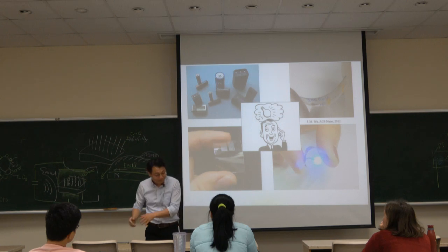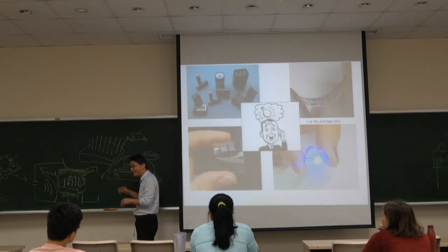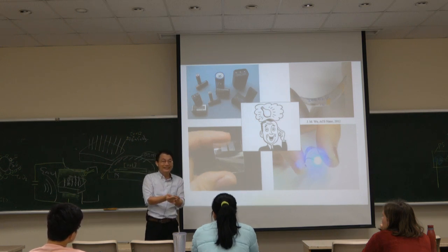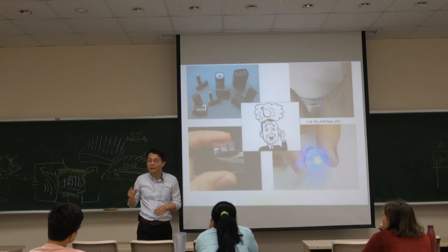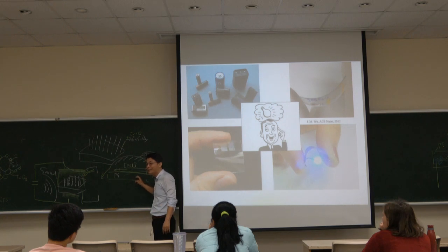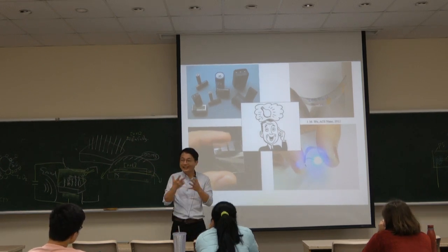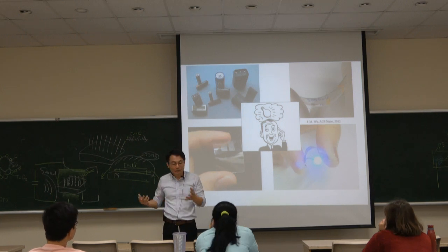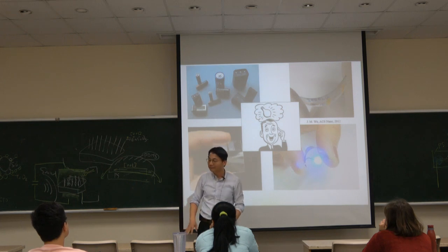And then after 10 minutes, I came back to see, wow, the PDMS was not curing, but the PS was deformed because the temperature was too high. I thought the PS should withstand at least 80 degrees. But we bought the PS substrate, and the temperature tolerance was very low. So I wanted to cry. I took 3 days, right? It was a very difficult, hard time for me. So everything becomes 0, right?